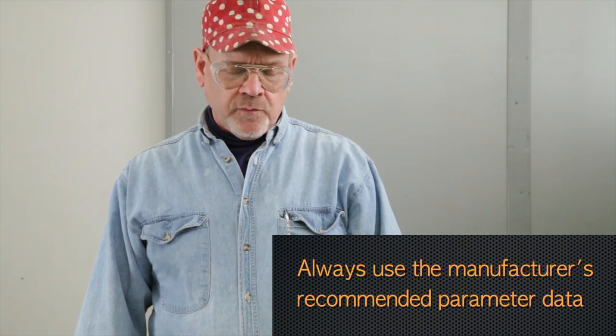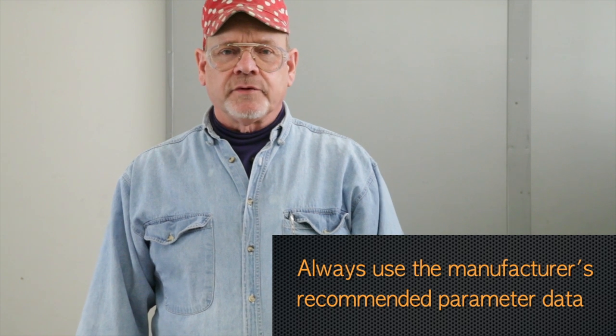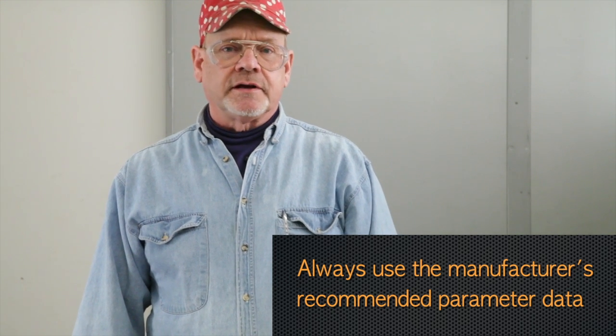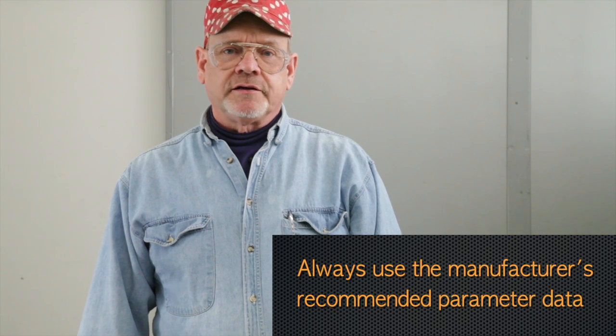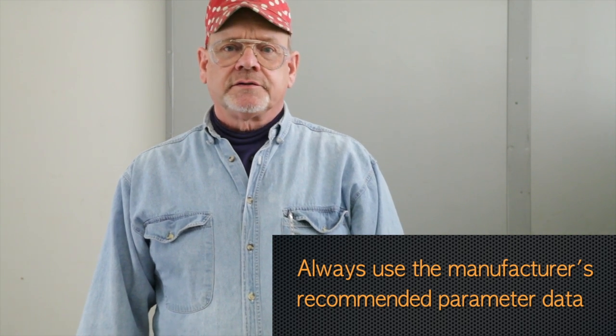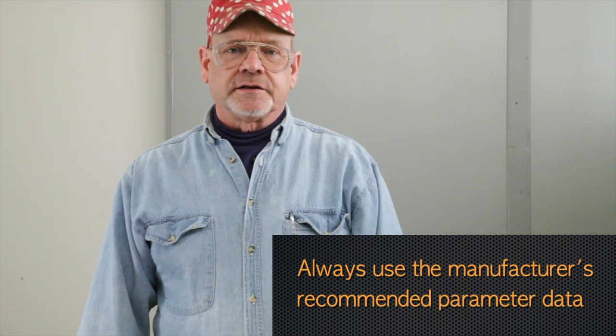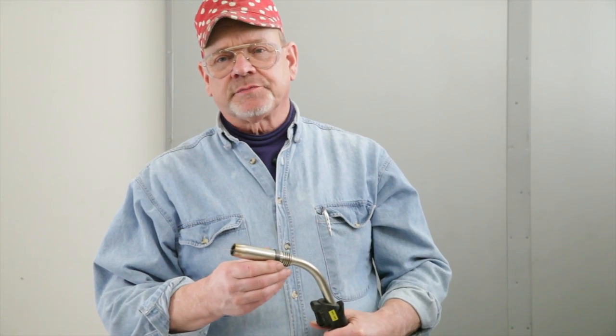It's important to note that there are many manufacturers of such equipment. For the equipment we're using, the parameter data is what we obtain from the manufacturer. In every case, check with the manufacturer of your equipment to get the best parameter sets for welding the copper-nickel alloys. In this segment, we'll do pulse gas metal arc welding with 70-30 copper-nickel welding wire.